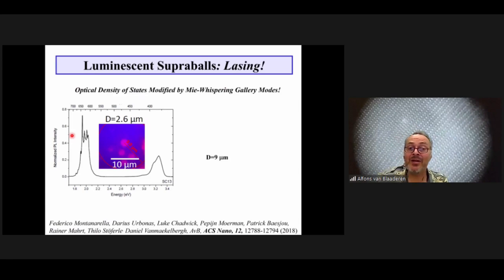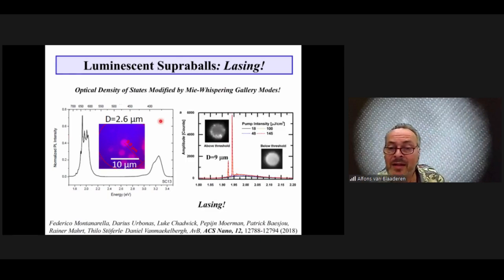being excited. And what is very exciting about this is that if we make the superparticles even larger, then these modes start to couple back, just as if they are two mirrors in a lasing cavity, start to couple back non-linearly, and we get lasing superparticles. So then the very broad red emission becomes very highly non-linear when we select one of these modes. So what we've now done is we've structured on the atomic scale these quantum dots so that they don't couple with their quantum mechanical wave functions, but they very strongly couple with their optical density of states, so strongly that we get nonlinear effects and get lasing superparticles.